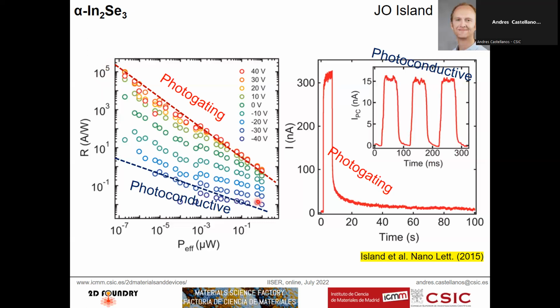In the photoconductive effect, if it were pure photoconductive, we would expect a flat line here, basically reaching 10 to the 0 amps per watt. Okay, that would be pure photoconductive. So still here, there is a little bit of photogating. But you can also see this tunability of the photoconductive mechanism, because if you are at positive gate voltages, it takes a lot of seconds to switch off this photodetector. Okay, so you switch on the light, it takes some seconds, switch off the light, and it takes several tens of seconds. Okay, so these are seconds.